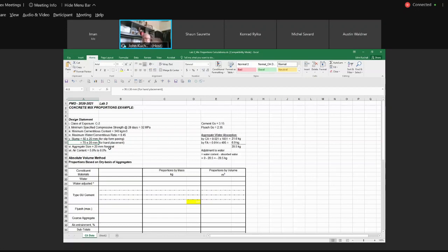If the slump is too wet, it's going to slump. You know, your nice straight vertical edges of your pavement, as it gets extruded from the slip form paver, start to slump. You don't want that. Okay. So in fact, on a slip form paving job, you'll find contractors will a lot of times reject concrete that's too wet because they can't work with it. Okay. Too wet. It's just as bad as too dry. You want to be able to work with it, it's got to perform. Aggregate size we know is 20 millimeter. That's the maximum size of aggregate.